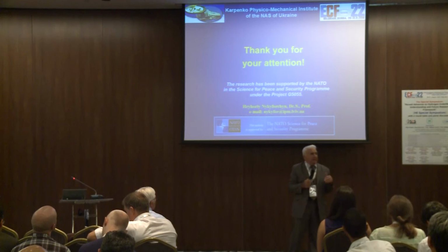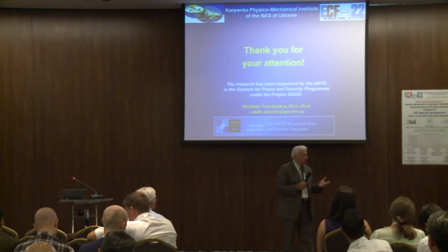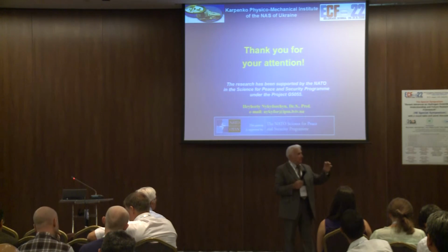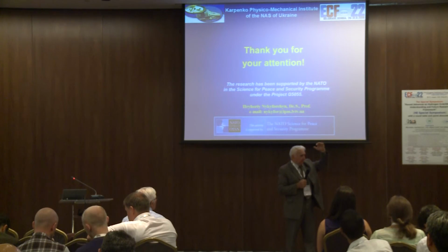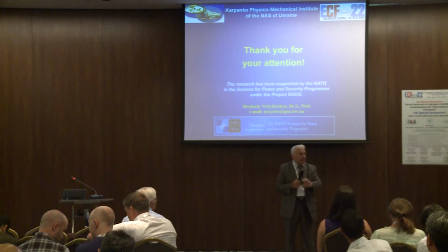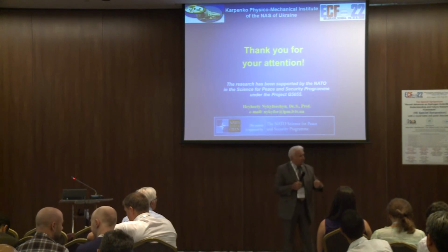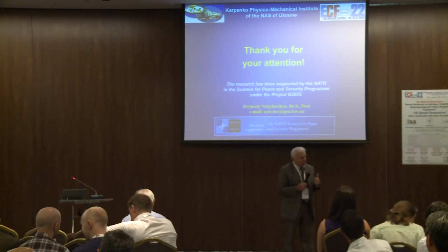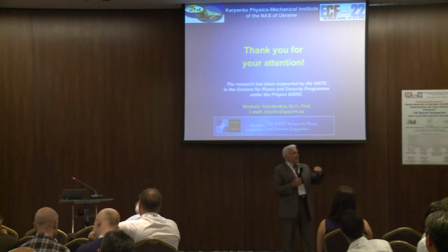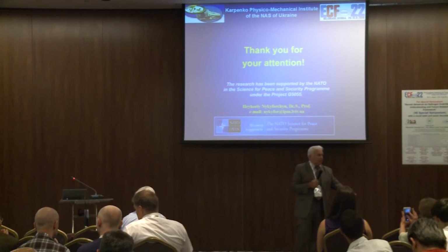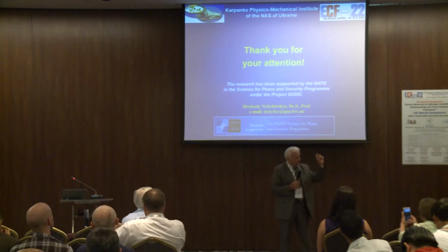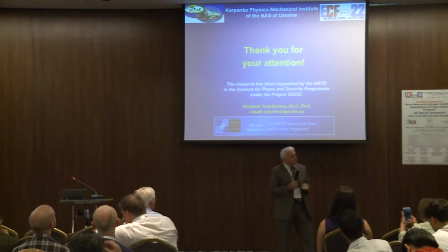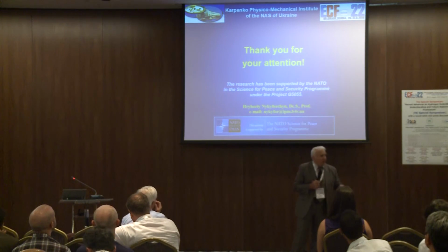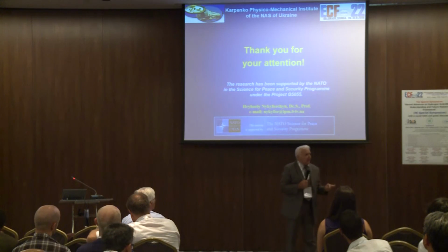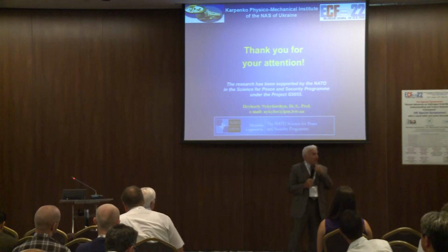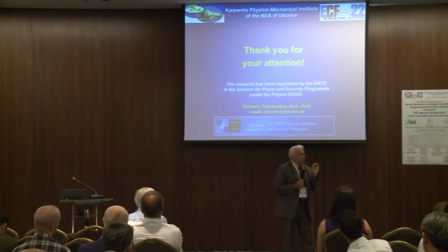We have absolutely direct confirmation of the role of hydrogen. For example, for oil pipeline steel, the upper part of the pipe and the lower part of the pipe. The lower part of the pipe is very brittle, where deposited water from oil serves as a source of hydrogen. And for example, for oil storage, the lower part of the oil storage where water is gathered on the bottom, this material of the oil storage is very embrittled because of the effect of hydrogen. Corrosion is the only source of hydrogenation.